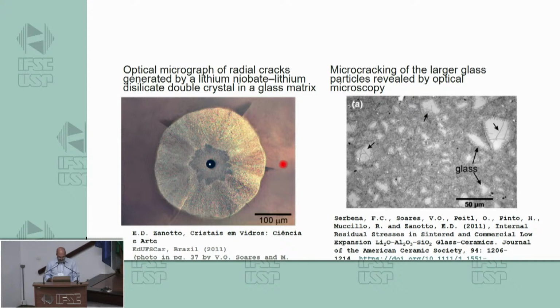Here again, I got some examples from the guys that are here. Chico, Zanotto. You can see cracks propagating from the crystal. That's because the crystal contracts less than the glass matrix below Tg. You have radial cracking. And here, cracking inside the particle that was crystallized on the surface, but due to the difference of thermal expansion coefficient, you have this issue.